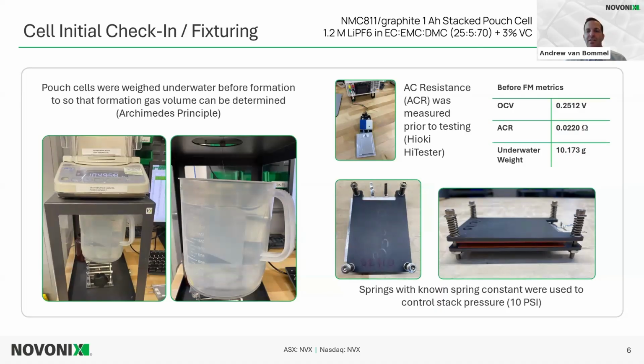So finally, when the cell is vacuum sealed, the first thing that we do is weigh these underwater. This is an analytical balance, and if you can see, there's a wire under the analytical balance, and it's weighing that cell underwater. So this initial weight will be used to determine the formation gas. When formation is complete, there's formation gas produced in the pouch cell. This adds buoyancy to the cell, so there would be a lower weight after formation, and we can use the Archimedes principle to determine the gas volume generated. This is a great method of determining gas volume, which we might want to compare between different cells, just showing one cell initially here.